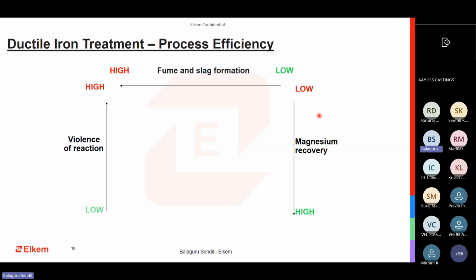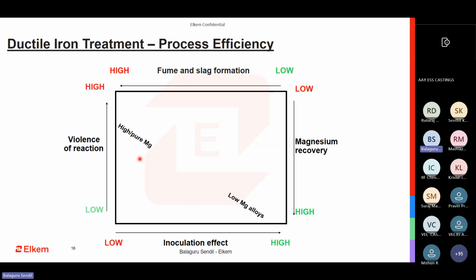When the reaction violence is calm, typically you tend to see very little slag as well as little fume. And then the magnesium recovery, the useful magnesium that you want, should always be on the higher side. You don't want to have very low magnesium recovery. And then whatever magnesium you're using should have some inoculating effect. We will touch upon that. It should also be on the higher side. If I take this as an axis, then I would like to be somewhere here where I have high inoculant effect, I have high magnesium recovery, I have very low slag, and I have very low reaction violence. So if I plot it, I have pure and then high. It is very simple.